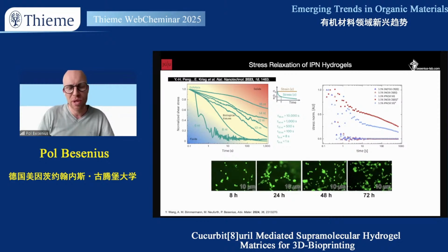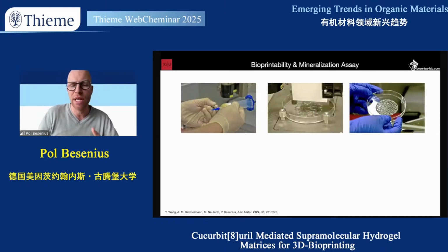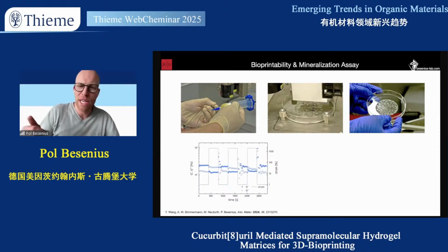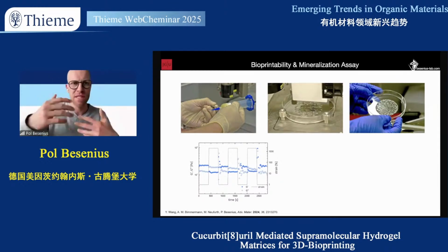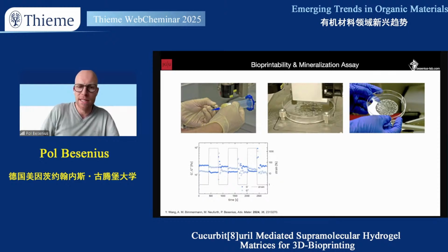The cells turn out to be very happy in this matrix. We can do functional assays. This is now just a couple of pictures showing that these can be printed. Now they are hydrogel either at room temperature or at temperatures of the cell incubator, 37 degrees. The reason why you can print this is because as you apply high strain, it starts to flow. So without strain, you have G prime higher than G double prime. So by definition, it's a hydrogel. But then if you look at this graph, you apply more than 100% strain, G prime and G double prime cross. So the viscous material properties dominate. It flows.